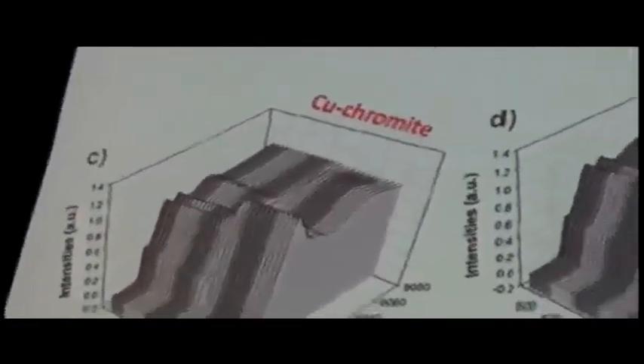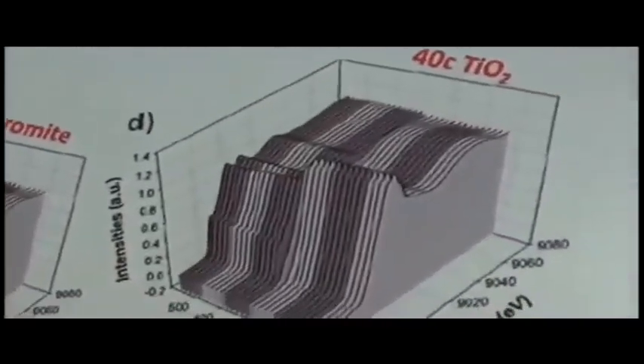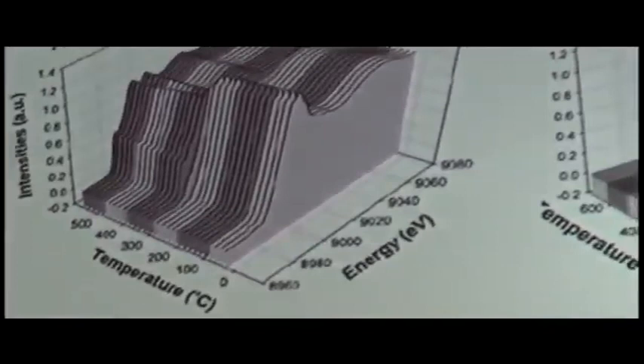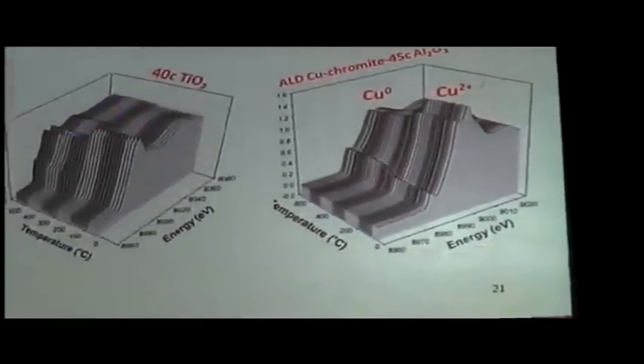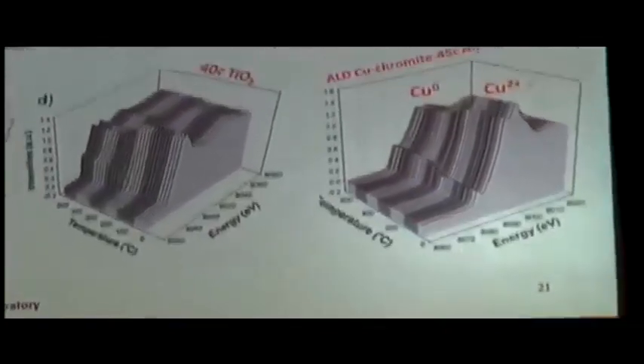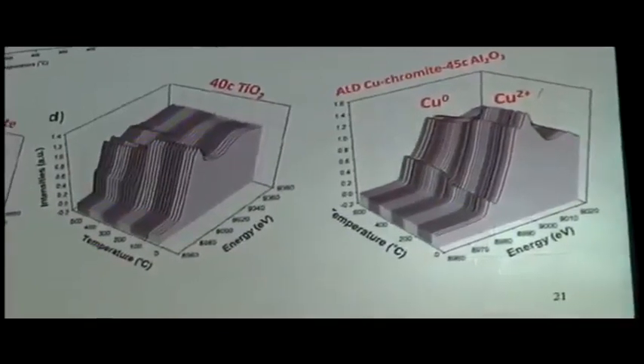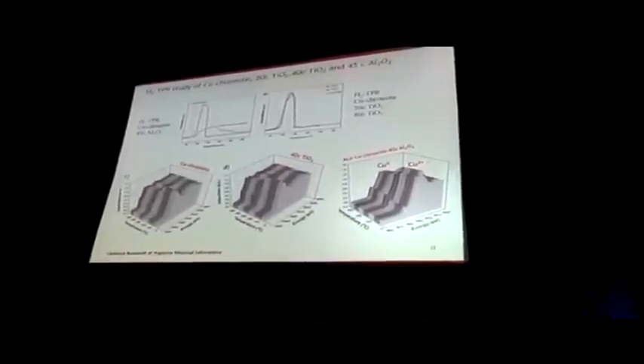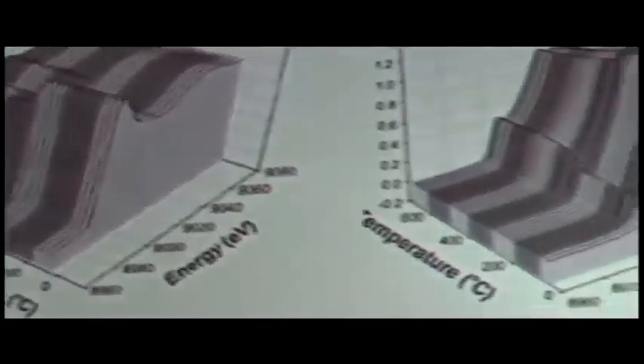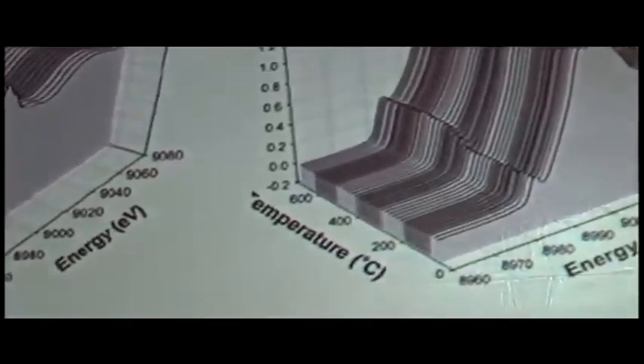So I've shown you now the XANES portion of the experiment, and what we do is we ramp the material up in flowing hydrogen. In section C there, you see the copper chromite material, and in D, and it should have been E there, is the one in which we've done 40 cycles of titania in the middle and 45 cycles of alumina. You can see by the XANES spectrum here that the redox chemistry is exactly the same for the copper chromite, the fresh copper chromite catalyst, and the one that's got those 45 cycles of alumina over it.